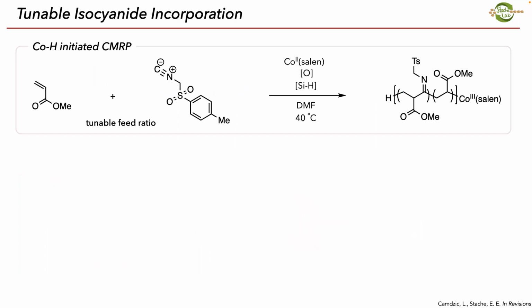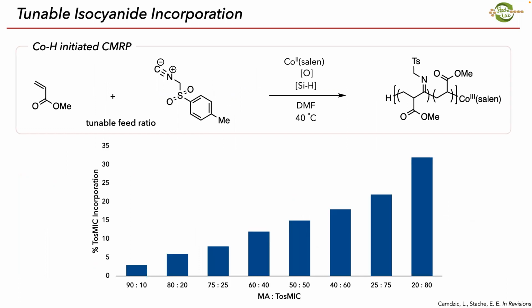And so we wanted to see if we could change the amount of isocyanide that's being incorporated into the polymer by changing the feed ratio of these two monomers, so methyl acrylate and isocyanide. And so she changed from a 9:1 feed ratio all the way to favoring isocyanide, so having that one in huge excess. And what she sees is an increasing, almost linearly increasing amount of isocyanide being incorporated into the backbone of the polymer, which was very exciting. So now we can tune how much of this degradable functionality we have in the backbone just by changing that feed ratio.